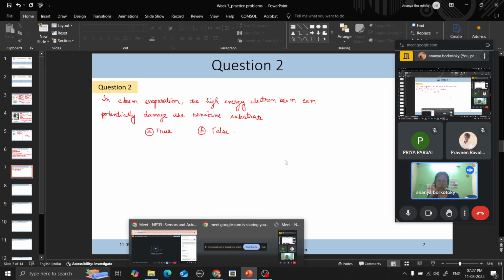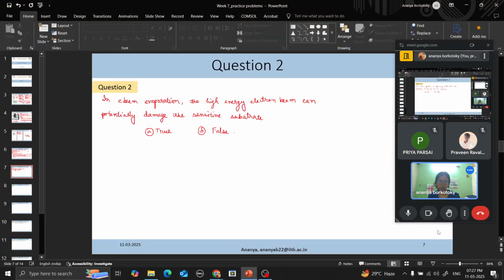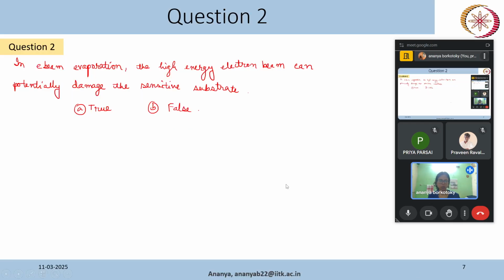The cause is heat generation, because we normally use e-beam evaporation for materials that have a very high melting point. The electron beam generates a lot of thermal radiation. We are melting material that has a melting point of, say, 1400, 1500 degrees Celsius, and that much heat is required for evaporation. In case of sputtering, it is different. We just hit the material and atoms are ejected. There will be some heating effect, but not that much. But in thermal or e-beam evaporation, that is the main process by which we do the deposition.